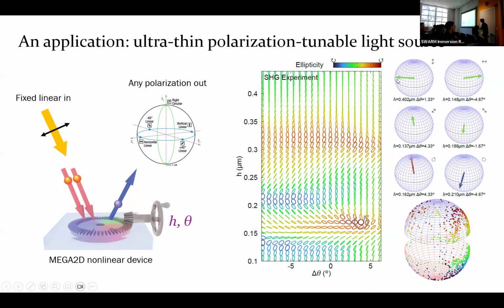So this is vertical polarization, this is horizontal polarization. These are the 45-degree polarizations, and this is the left circular and right circular polarized light. So you can see that we can almost cover the entire Poincare sphere just by playing with the spacing h and the rotation theta. And this is done without changing the input, right? The input is fixed. It's just a fixed linear polarization. And we're only changing the h and theta, which are internal to this interface.